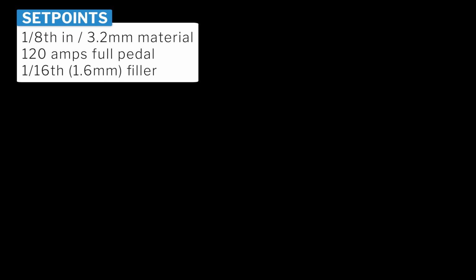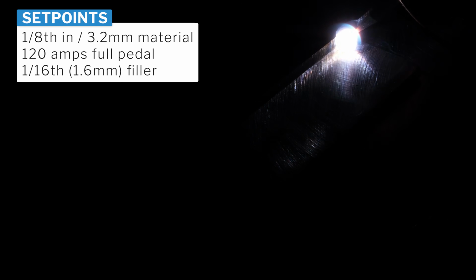So to start things off, we're going to use 1/8 inch material. I'm going full pedal. I'm not using the foot pedal for amperage control, nor should you when you're learning at first. I started the arc, allowed the puddle to cross over between the pieces, and in this case I'm aiming at that top edge more so than a flatter angle into the joint. And this is a fusion weld, so I'm just melting off that top edge primarily into the bottom plate and creating a weld that way.